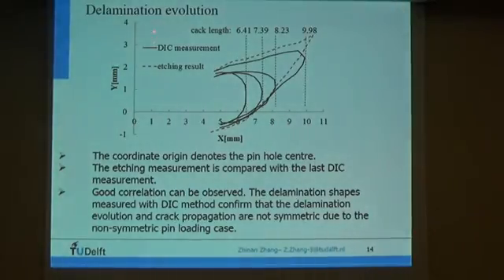So we can see from this picture, it is the history of delamination extension, and the origin here is the pin loading pinhole center. The solid line is the measurement, and the dashed lines are the history of the delamination. So a good correlation can be observed. The delamination shape matched with the DIC system confirms that the delamination evolution and propagation are not symmetric due to the non-symmetric pin loading case.